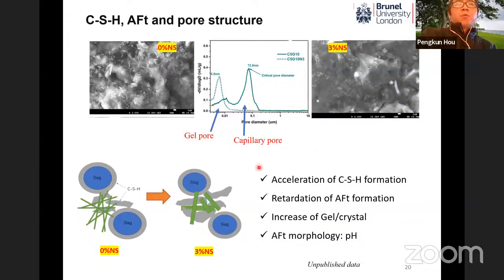So with this, we can draw this kind of picture showing how the nanosilica affected the microstructures. The previously porous crystal, the AFt and the CSH gel structure can be turned into a very compacted, more CSH gel and less AFt structure. And actually, I want to say that AFt morphology has also been changed.